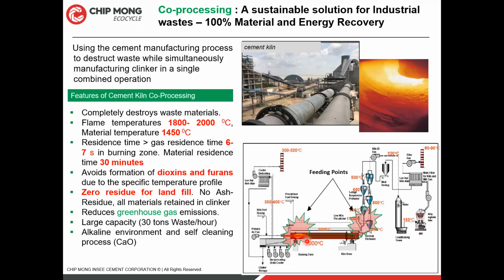And another thing is, with this specific temperature profile, we can avoid dioxins and furans. Even with the higher temperature in the combustion stage, there's no dioxin furan. We can avoid the dioxin furan formation. At the same time, in the post combustion, due to the residence times as well as the kiln design, there's no sudden cooling, so we can avoid the dioxin furan.